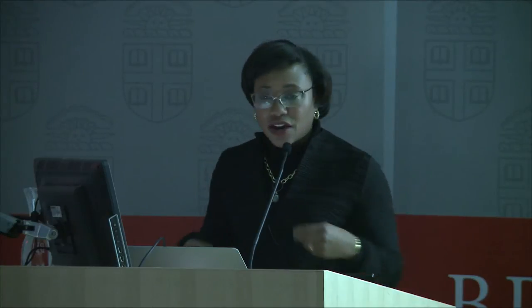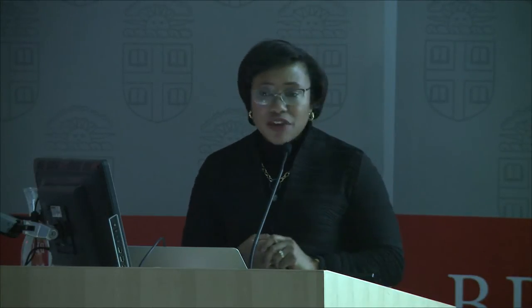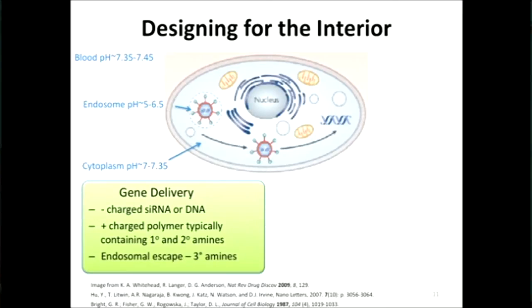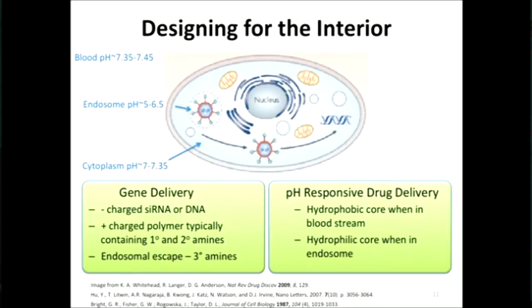Well, to do that, we have to essentially design polymer systems that are intelligent, so to speak, in that they respond to their environment. And there are several ways in which we can do that. If we're trying to deliver genes, and we'll talk about that in a minute, we need to be able to encapsulate the gene using charge and then release it when it gets into the cell. And if we're encapsulating drugs, then we want something typically that's going to be hydrophobic and will allow the drug to sequester inside your nanoparticle. And you also want something that's going to release when it's inside the cell.